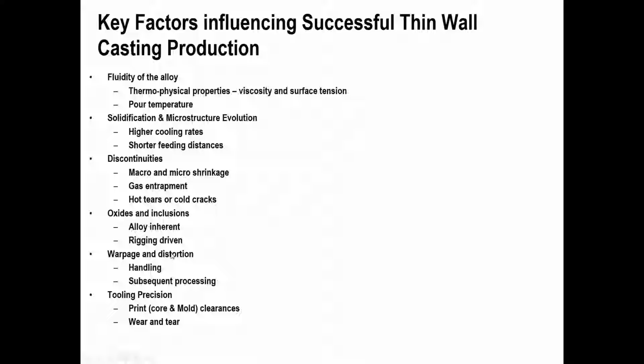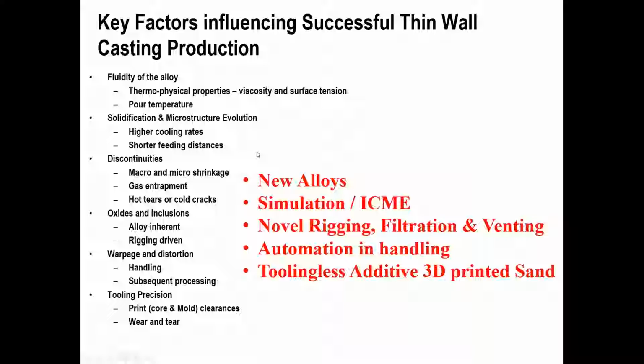And then the precision of the tool contributes quite a bit to the success of the thin wall casting, especially your print clearances between the core print and on the pattern and in the core. And then normal wear and tear do add to changing those clearances and then ultimately affecting your final wall thicknesses. So how do we mitigate or come up with these obstacles and make successfully thin wall castings? Obviously new alloys which have better fluidity, rigorous simulation, ICME tools used, novel risering, gating, filtration, and venting scheme that you would need with thin wall. I would say automation in handling.